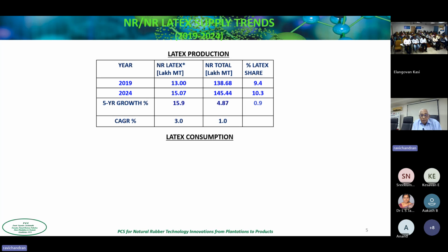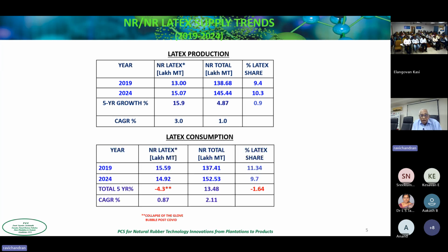So coming to latex production, we have today 15 lakh metric tons of latex out of a total of 145 lakhs of natural rubber. So the latex share is 10.3%. And the growth rate has been 3% for latex and 1% for natural rubber. This period is low because of the COVID effect. But it's picking up, and I expect we'll be back to 6 to 8% growth in 2025 to 2030.